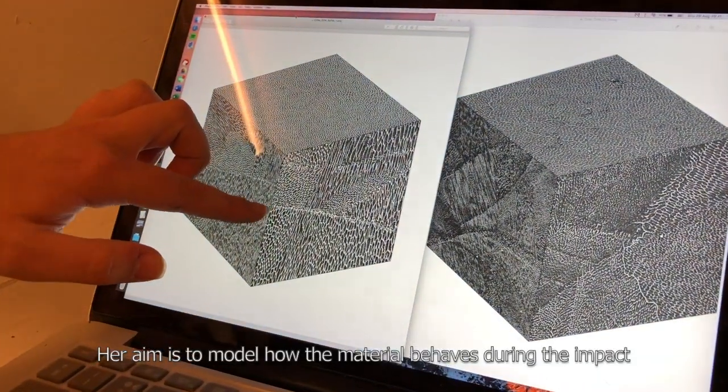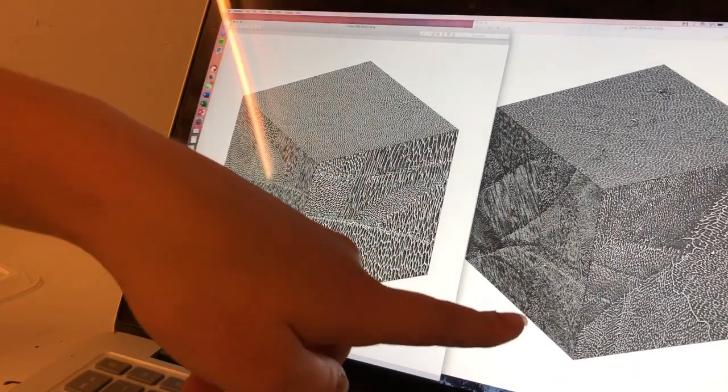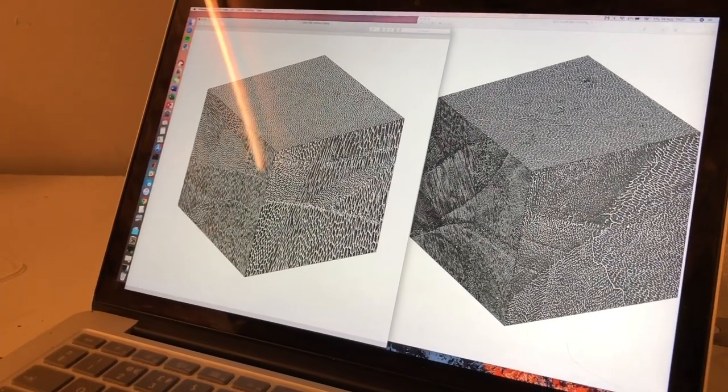You can see in this image, because it's 3D printed, you have micro-cracks between the melt layers of 3D printing. But this is the heat-treated version and there aren't any micro-cracks. They've disappeared as it's been heat-treated.